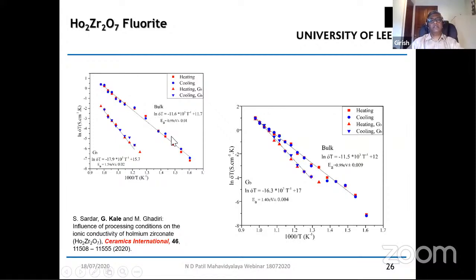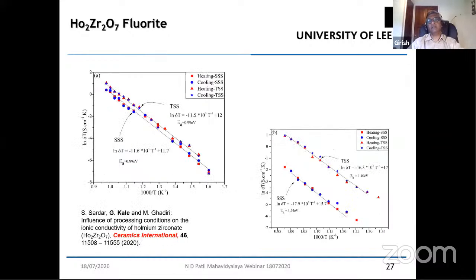The only advantage of this material is that it is much more stable thermodynamically compared to, say, materials such as ceria gadolinium, and almost with similar thermodynamic stability as yttria stabilized zirconia. So the challenge for us in the future is how to improve this conductivity to a better value that is then made suitable for fuel cell application.